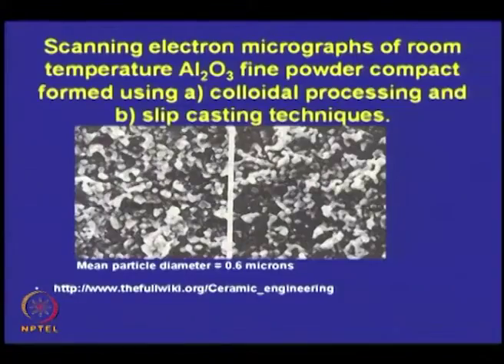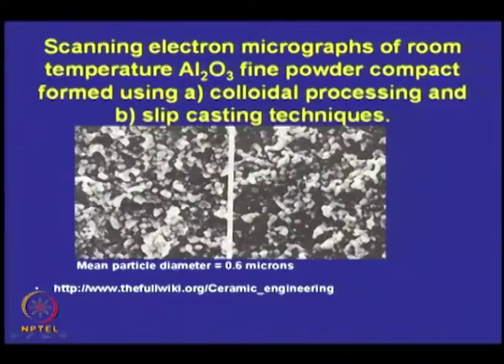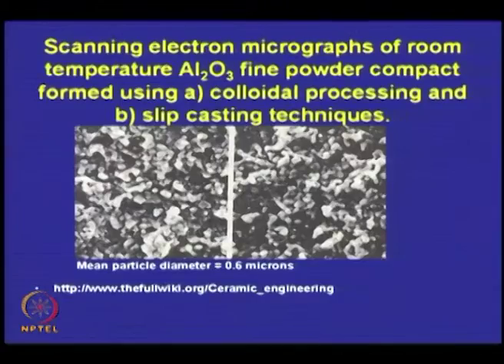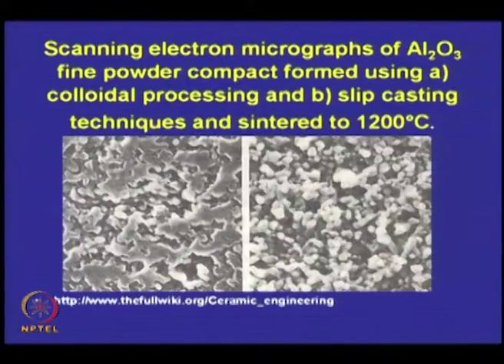But before I take on sintering, let me bring up something I said in my earlier lecture about how they are compacted. Here is a case where identical sized alumina fine powders were taken and compacted by 2 processes. One is colloidal processing, where the particles were taken in colloid form and allowed to settle down. The other was slip casting, the way your bathroom fixtures are made. These were fired at 1200 degrees centigrade.